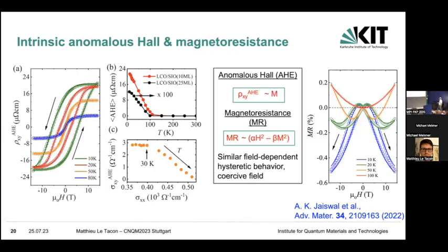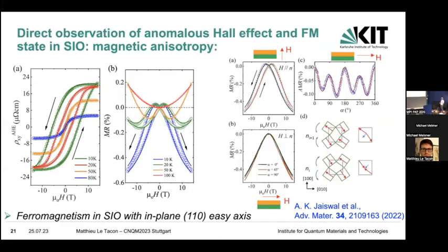And last but not least, we can also measure the magnetoresistance. Now we do have a metallic compound, so the magnetoresistance depends on the square of the field, but there's also a component that depends on the magnetization, and that also shows a field-dependent hysteretic behavior with a strong coercive field, in good agreement with what we've seen from the anomalous Hall effect. We can look at the angular dependence and deduce from that that the ferromagnetism is in the strontium iridate layer with the in-plane 110 easy axis.